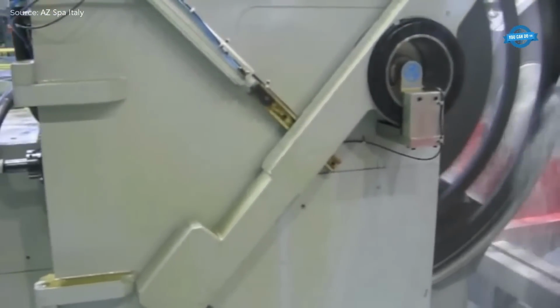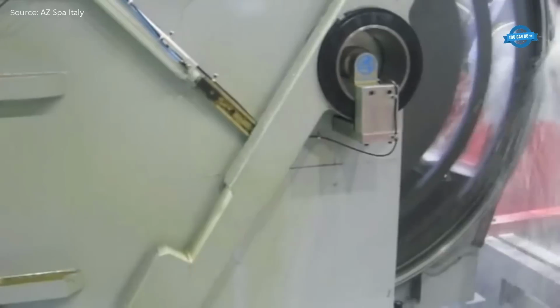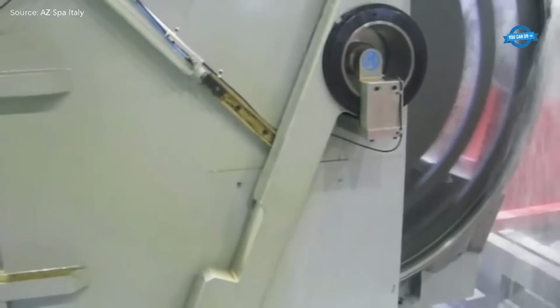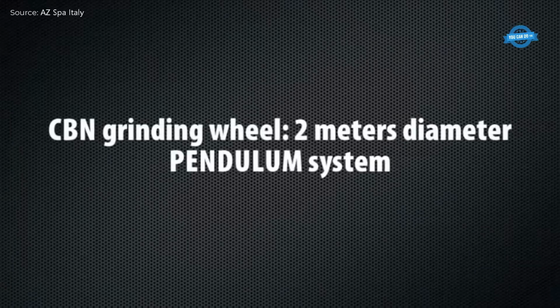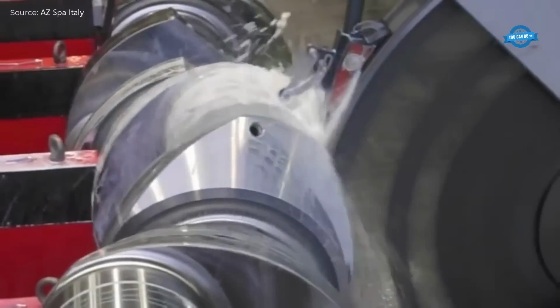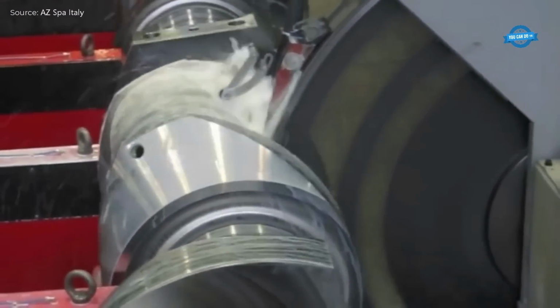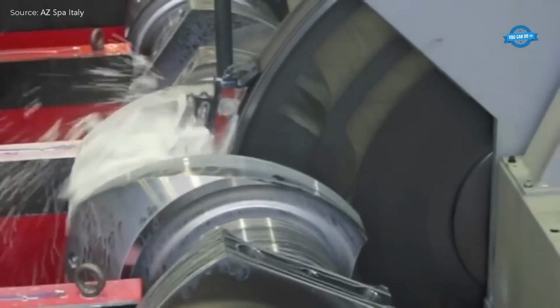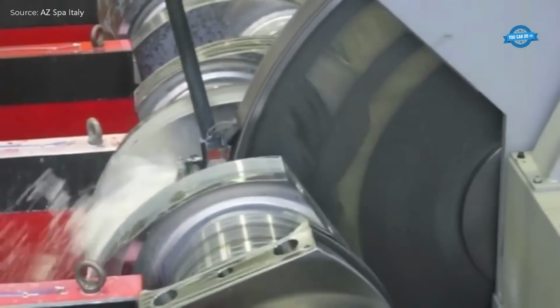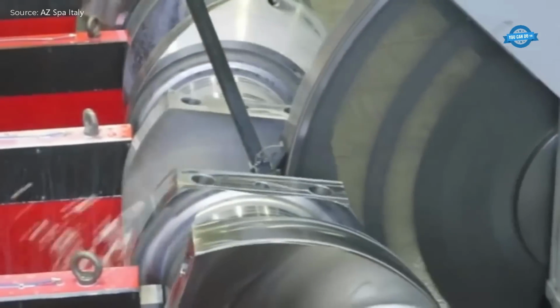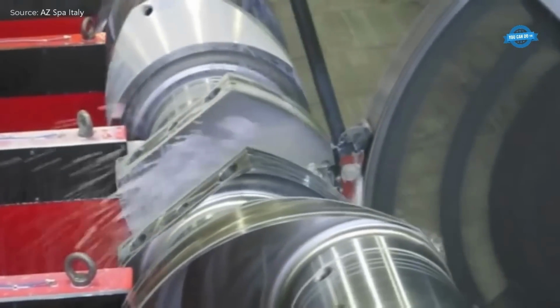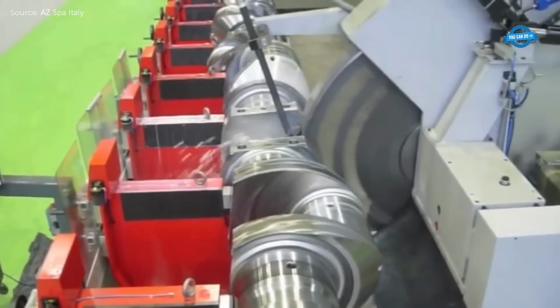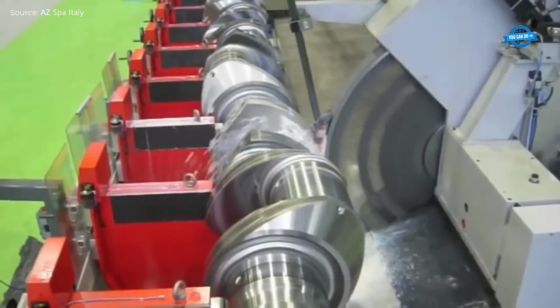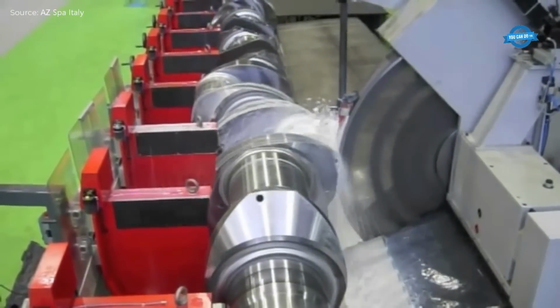Forging and machining. Forging processes involve the use of massive hammers or presses with forces exceeding 12,000 tons. Precision machining follows, removing up to 30% of the raw material to achieve the final geometry. Heat treatment. Crankshafts undergo induction hardening or nitriding to enhance wear resistance. This can involve surface temperatures of over 900 degrees Celsius and cooling rates of 100 degrees Celsius per second.